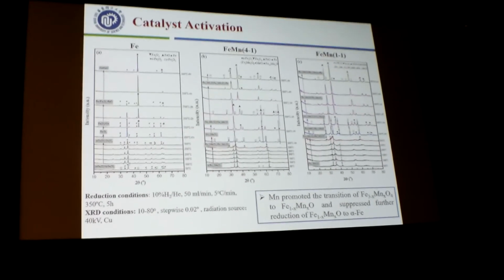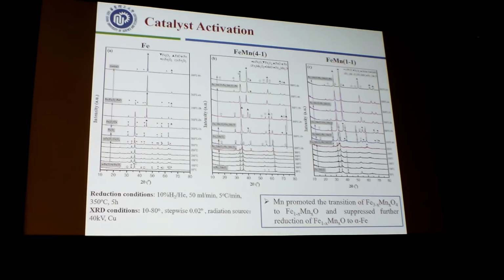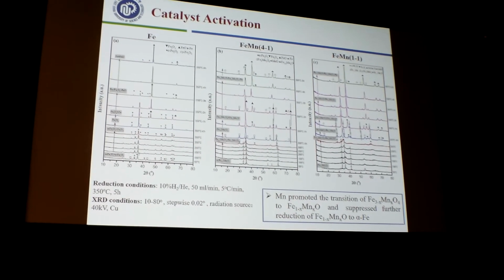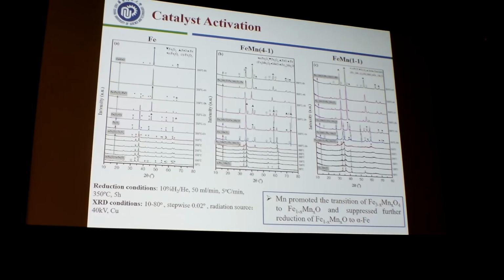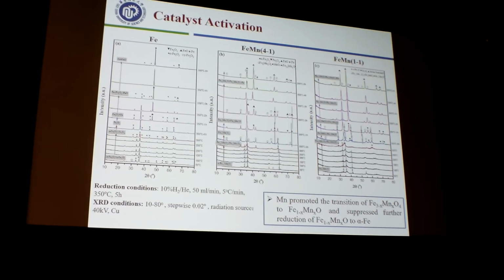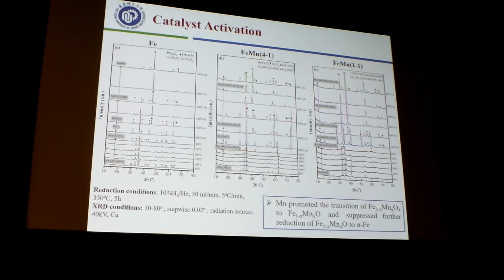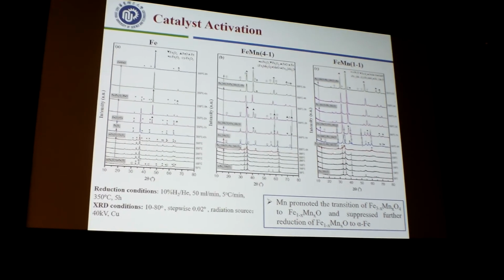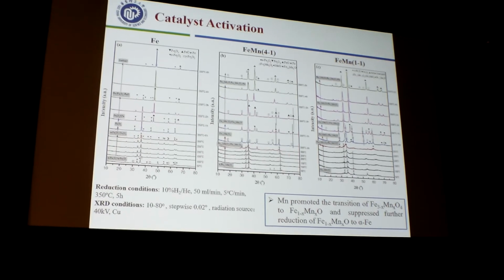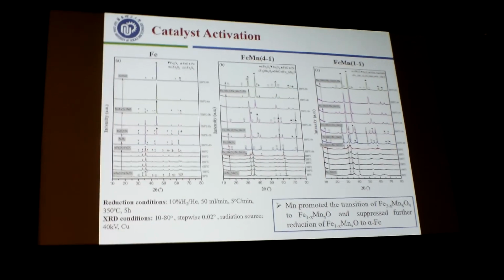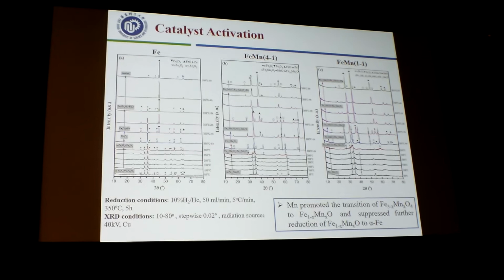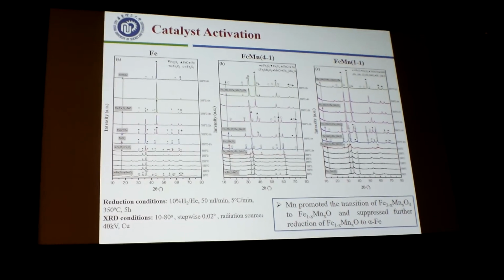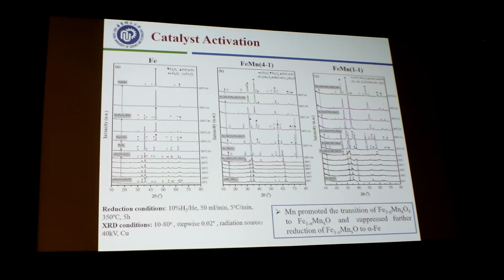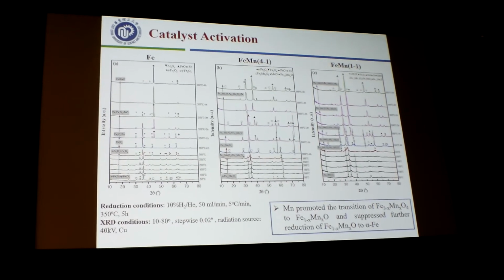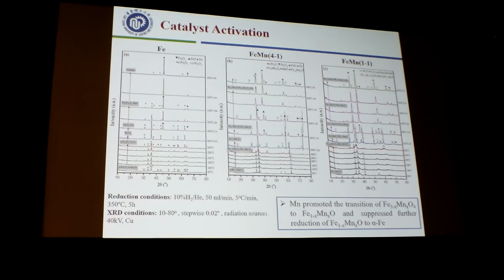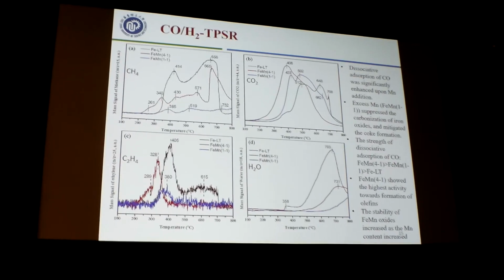So we also did some in situ XRD experiment to visualize the reduction behavior of the iron catalyst. And so we again observed that the manganese promoting the transition of the iron manganese oxide to the iron 2 oxide, but the further reduction of the iron 2 oxide to iron was suppressed.